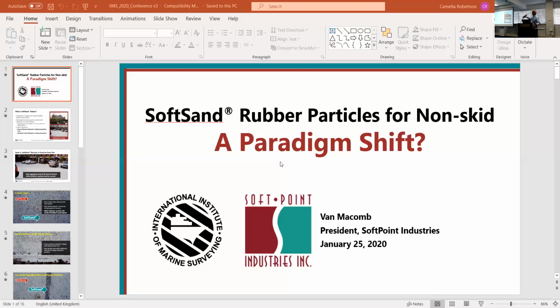So this particular company was having a problem with aggregate and was actively searching for a solution to the problem of aggregate coming loose in the coating. They had tried all the minerals: black beauty, silica, sand, and whatnot. They'd even tried a lot of scrap rubber materials, which is getting closer to a solution, but a lot of the scrap material is a different polymer system.